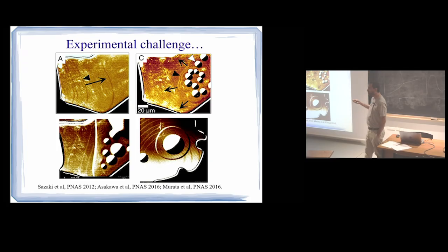At low temperatures, ordered crystals usually grow by spreading. You have an ice crystal with a flat surface, then some step forms, and this propagates horizontally. And that's what we're observing. So just by the mere fact that we are observing stripes, we know that we must be a little bit supersaturated.